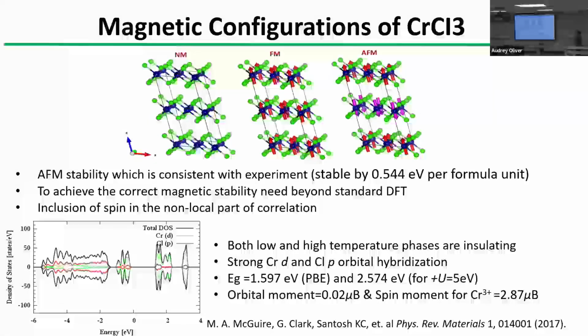the total energy, right? In that case, if you just use standard DFT, it says ferromagnetic is the most stable, right? But if you compare with the experiment, that's not true. Antiferromagnetic is stable. So since we have this magnetism, we are not taking something into account there, that interaction. If we use, for example, U, this is called Hubbard U, an on-site Coulomb interaction correction, then we can actually reproduce the stability as well as the magnetic moments, right?